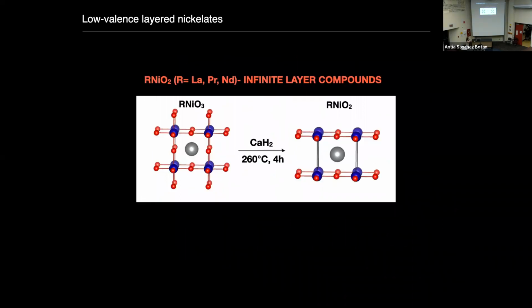So let me show you how that works, at least for one material of the series. That is the infinite layer member. That's this RNiO2 material, or 112 material. So here again, we have our nice layered phase with our NiO2 planes that are separated by a single layer of the rare earth ions. But again, the way in which we get to this material, it's from a parent phase, that is this perovskite phase, or 113 phase, in which we do have apical oxygens. So what they do is they put the material in a hydrogen environment in very tricky conditions, or so I'm told. And that's basically how you end up with your nice layered phase.